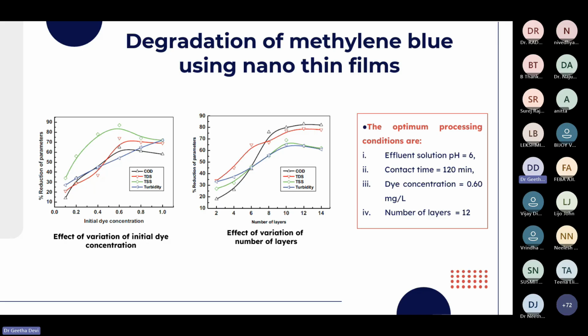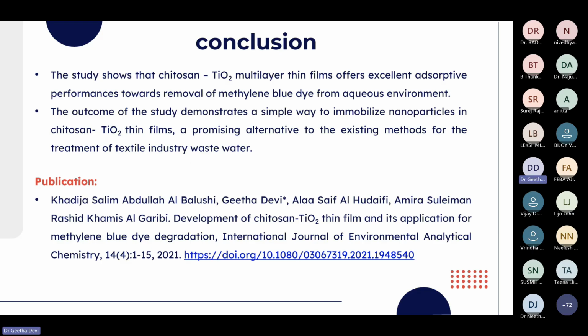And we could see the optimum values are effluent solution pH of 6, contact time of 120 minutes, dye concentration of 0.6 milligram per liter, and number of deposition layers of 12. This study shows that the chitosan titanium dioxide multilayer thin film has excellent adsorption capacity, and it also requires a very small quantity of material, since it is coated over the surface as nano layers. And this same slide can be repeatedly used for further degradation stages,